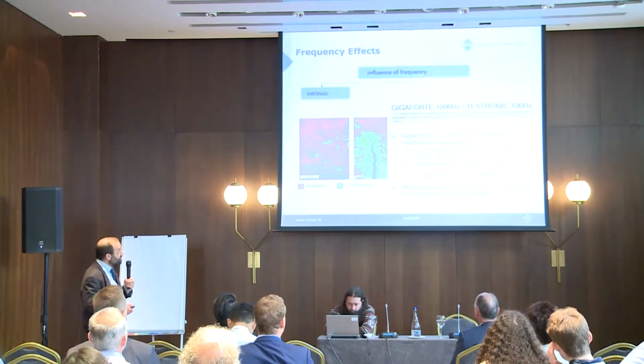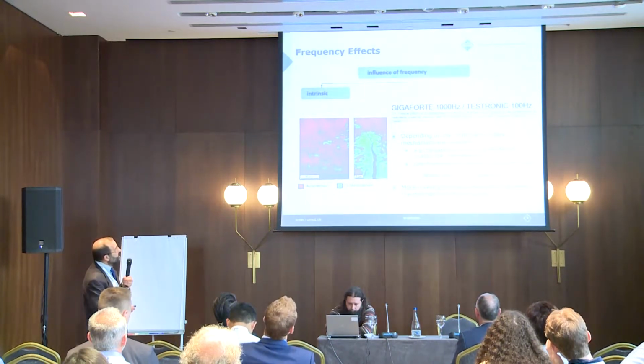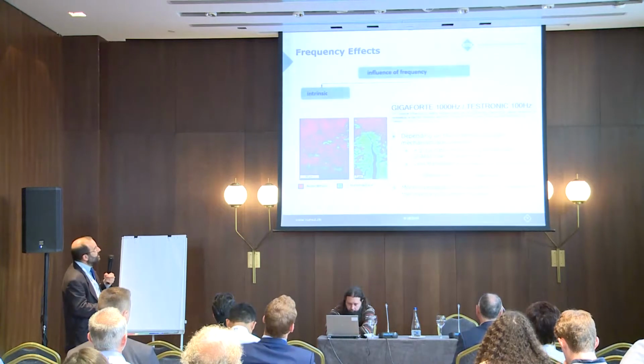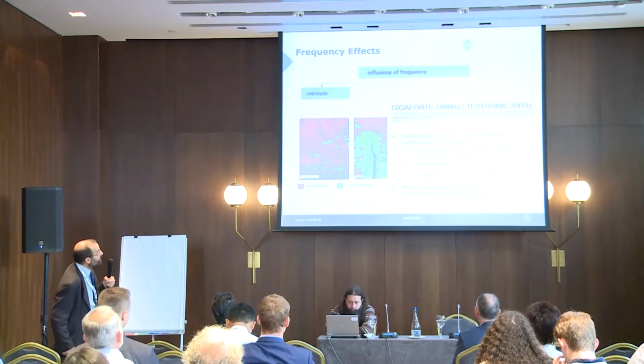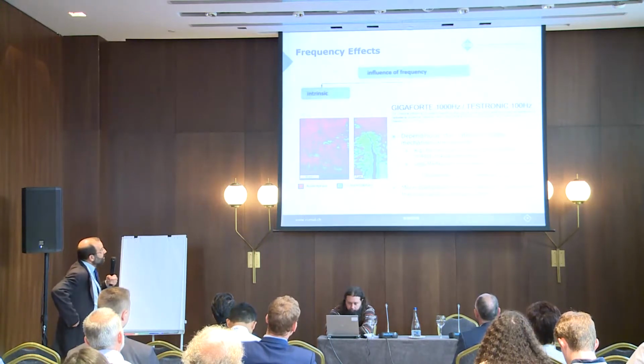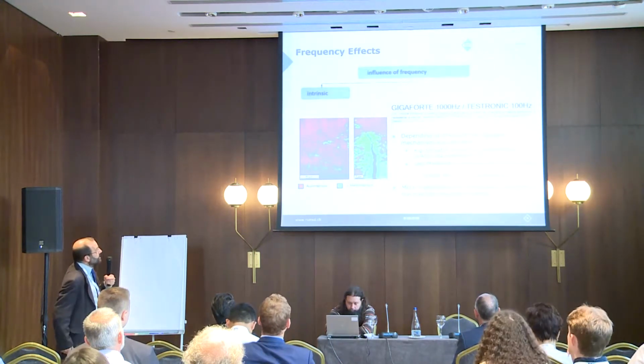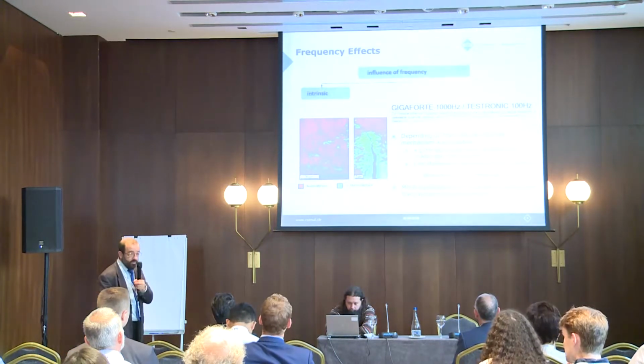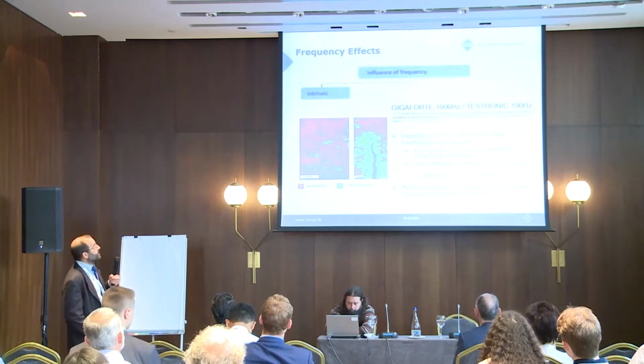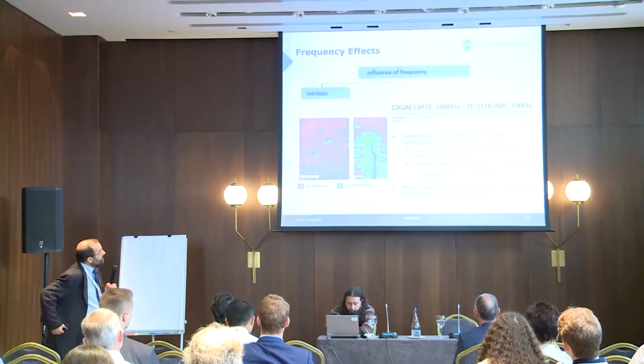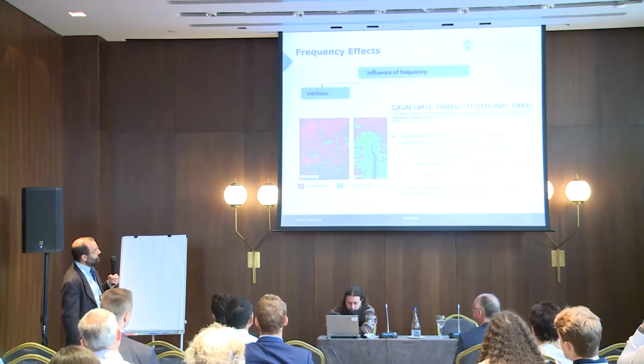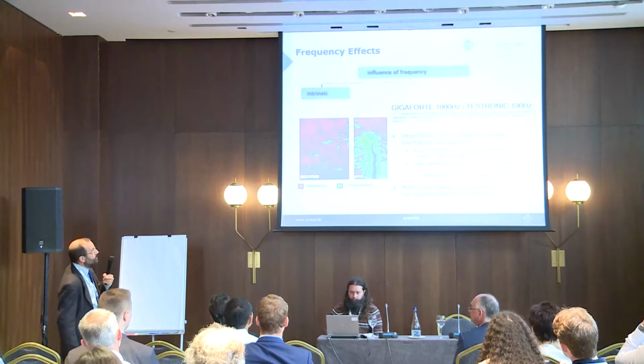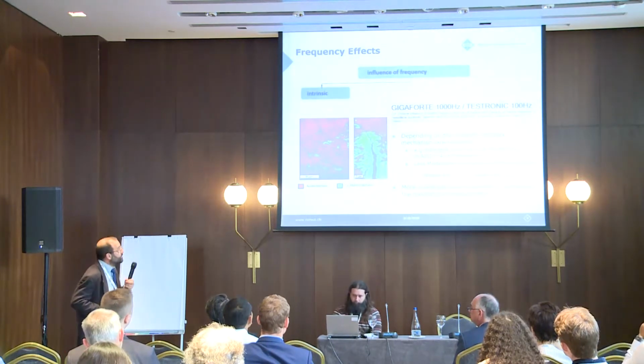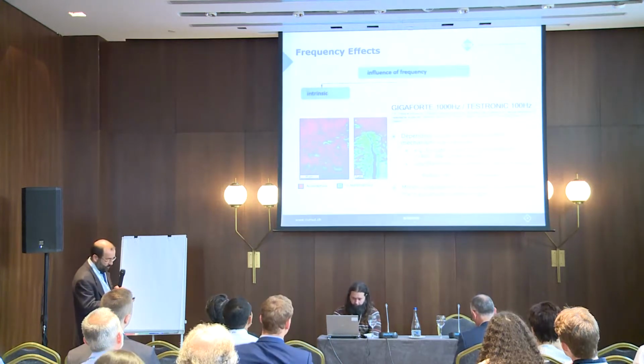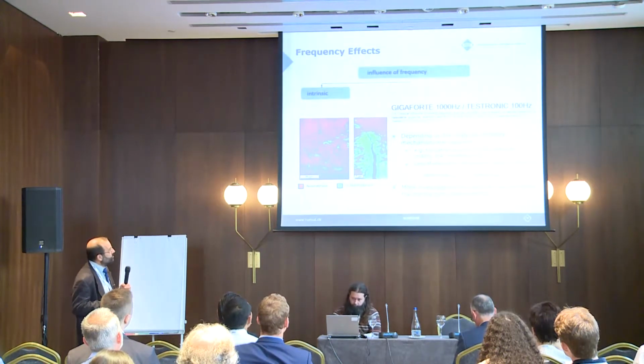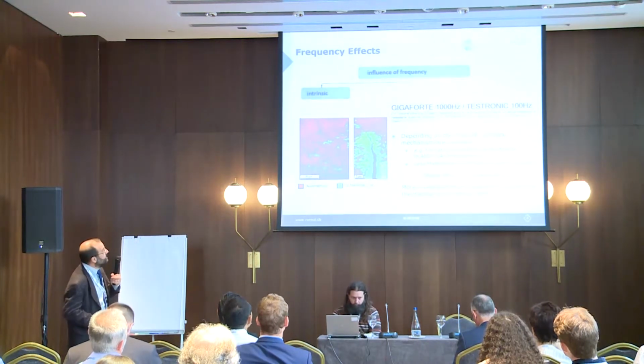He used two resonance fatigue testing machines, one running at 1000 hertz, our new system, and a traditional resonance testing machine running at 100 hertz, and he could find a very interesting effect that testing this austenitic steel, he could find that less strain-induced martensite is formed at higher testing frequency, leading then to a smaller crack growth rate. So by having two similar systems, also quite small effects can be detected.